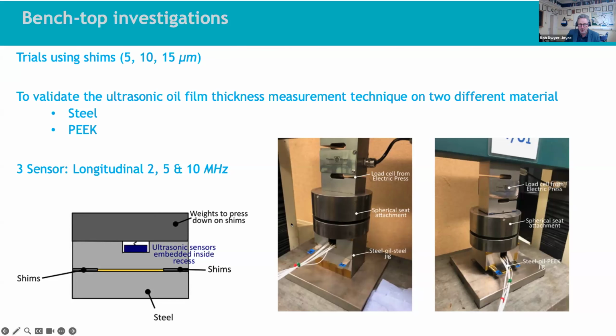So we've done some benchtop investigations, putting shims. It's really quite hard to generate an oil film in the lab. How do you generate a 5 micron, 10 micron oil film in the lab to test it? And it's quite tricky. The way we do it, which is not perfect, is we use these very thin shims of metal, which we squash between two blocks of flat material. We put a drop of oil in there, squash it down, generally put a weight on top. Here it's put in a press with a load cell to squeeze it down nice and tight. And we hope that our oil film thickness is about 5 microns if we use 5 micron shims, or 10 microns if we use 10 micron shims, etc.